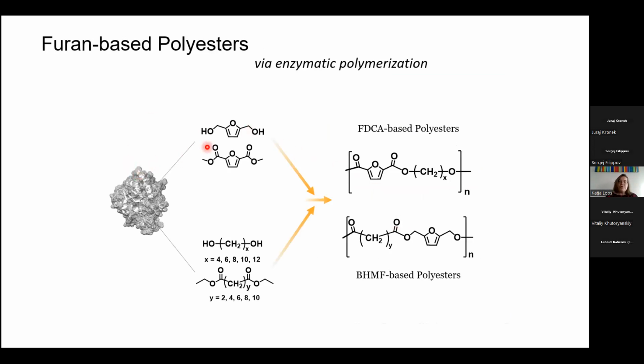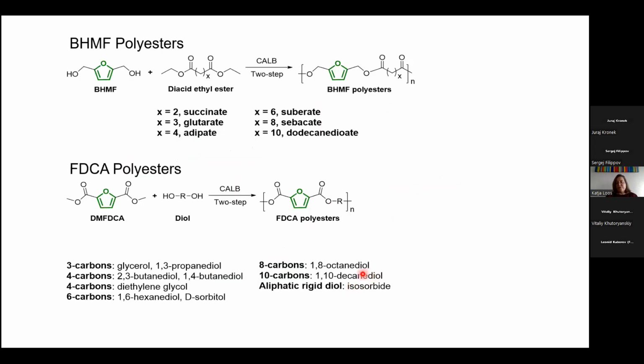So in principle, what you do, you have the HMF or the FDCA, and you co-feed it a flexible counterpart. And then you have the FDCA-based polyesters or BHMF-based polyesters. And we also already did a lot in this field. So of course you cannot just do PEF, but also a lot of others. I already told you that it's very difficult by normal melt polycondensation to polymerize this. But for the enzyme, it really doesn't matter, because you don't have too high temperatures. So we could report a lot of BHMF-based polyesters, but also a lot of FDCA-based polyesters.